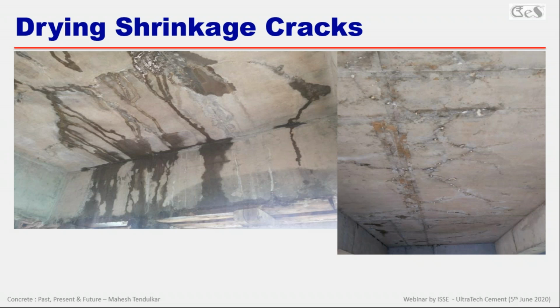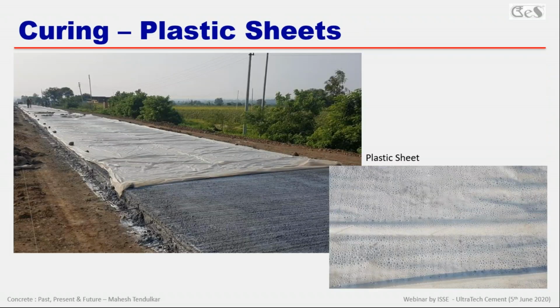Even in the slab, you can see cracks will start from the top and not from the bottom, because the bottom shutter is retained. So a high surface area is exposed in a concrete slab, and from there water from concrete will evaporate and definitely it will start cracking. So the best way of protecting concrete is by use of plastic sheet.